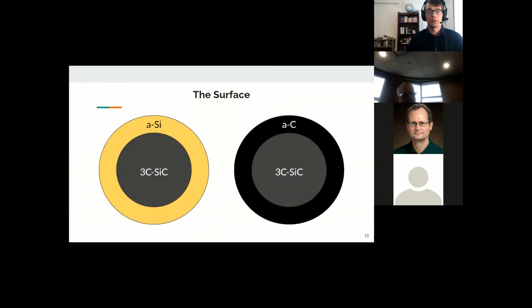As was alluded to before, the surface of the silicon carbide nanocrystals can either be silicon or carbon-rich, and that's usually in the form of amorphous silicon or carbon. The solubility of the nanocrystals in alcohols strongly depends on how much excess amorphous carbon or excess silicon is present in the sample. Research on amorphous carbon coatings is significant, and there's even some commercial products available that utilize the technology, such as scratch-resistant thin films. Carbon as a shell has potentially useful properties due to the many bond hybridizations available to the carbon material system. Despite its potential for functionalization, excess amorphous carbon on the surface has the potentially negative impact of decreasing the solubility of the silicon carbide nanocrystals in alcohol solvents.